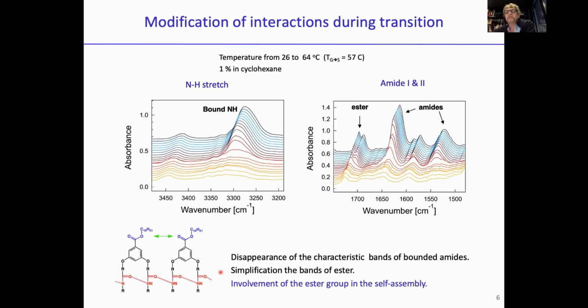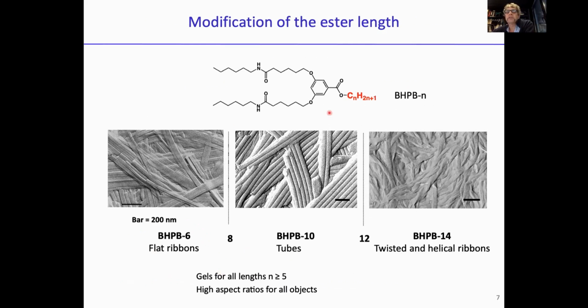And because we have chemists in our group, we decided to explore this to obtain different kinds of objects. We varied the length of the ester in BHPBN, and we synthesized about 20 compounds. What we observed is that when the length of this ester is lower than 8 carbons, the self-assembly looks like flat ribbons, which you can see here. They still form gels, meaning that we have high aspect ratio objects, like long fibers. Between 8 and 12 carbons, we have these pictures. I will blow up this regime in a few minutes. And above 12 carbons, we have twisted and helical ribbons, like you see in these pictures.